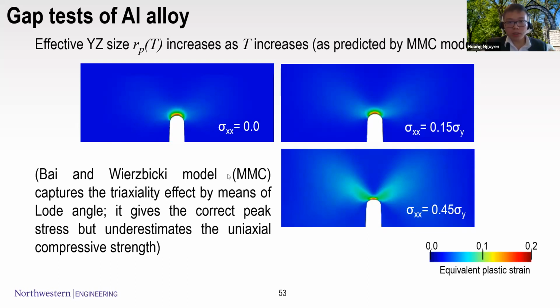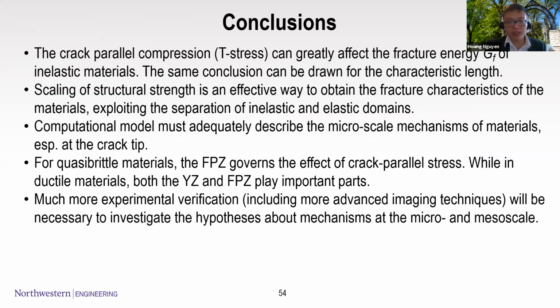However, right now the quantitative result is not as promising, so we are doing some training of the microplane model for such a behavior. In conclusions, the crack parallel stress should be considered when you have the fracture energy of the inelastic materials, and the same conclusions can be drawn if the materials have any characteristic length that can interact with the triaxiality of the stress state at the tip.